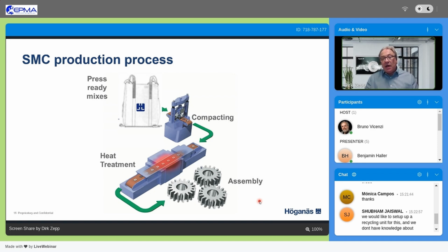Unfortunately, most of the designers are used to consider additional mechanical operations afterwards, because they come either from the PM materials, so normal sinter parts, or from full metal components, and they don't see at the beginning the need to have an assembly-ready design available, because any kind of mechanical operation can damage or destroy the insulation coating that we are putting on each particle during the annealing process. And unfortunately, this insulation coating is exactly the magic of the SMC material.